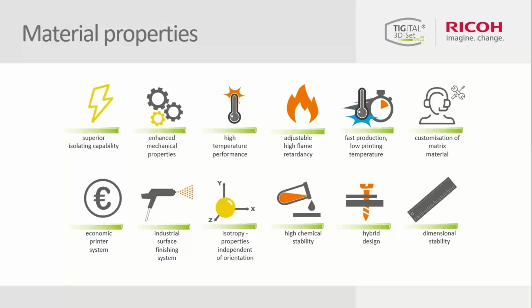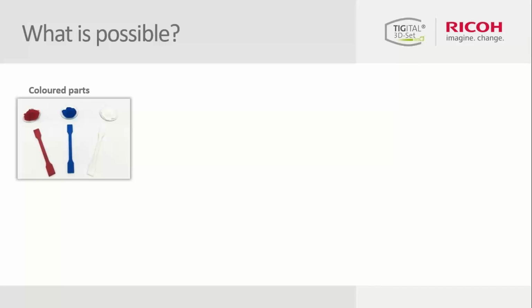And coming to the last point, dimensional stability. Because of the low shrinkage of the materials, because we are amorphous systems, it enables you to print huge parts. And if we look at what is possible with our materials, we are able to produce the powder itself in different colors, starting from red, blue, white, or any different colors which you need. And as I mentioned, because of the low shrinkage, you can print really large scale parts.